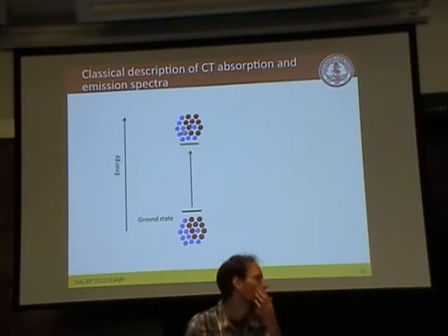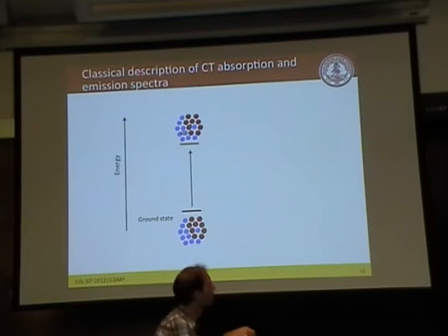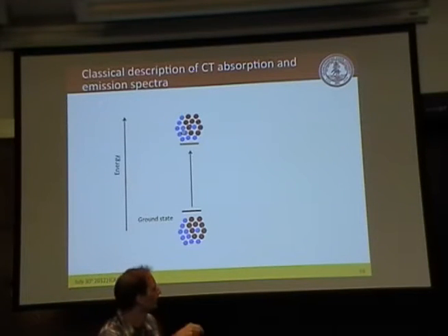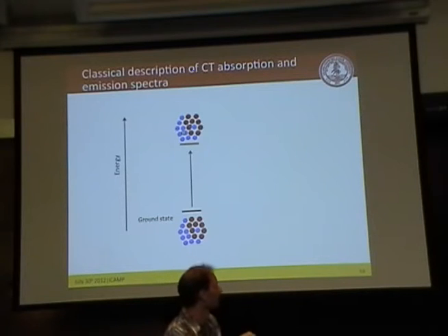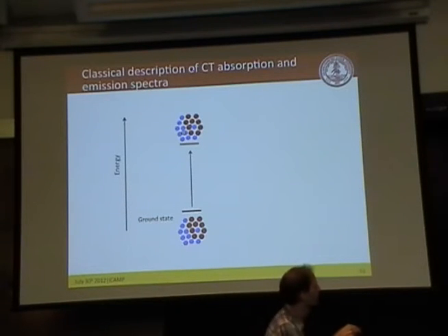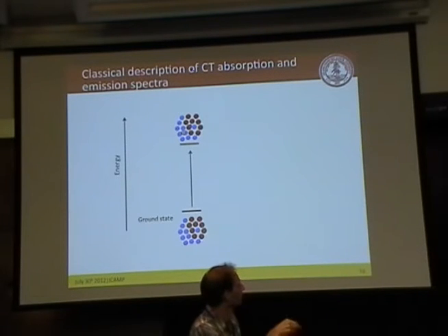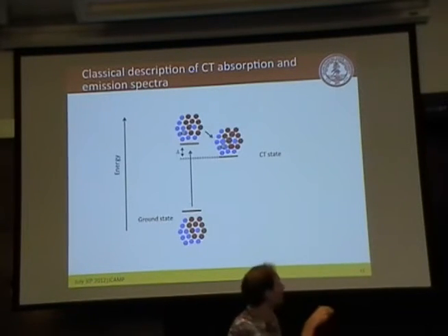Therefore, I want to show you this slide. Now you have to really think on the molecular scale. What is happening when we excite into this extra band, this very low absorption? You start from a material in its ground state, which just means it's in the dark. And you have a very small chance, that's why it's a weak absorption, that you can excite this to the charge transfer state. The charge transfer state is the hole on the donor and the electron on the polymer, on the fullerene, for example, like this. So immediately upon absorption, you create this. But this is not stable and will relax.